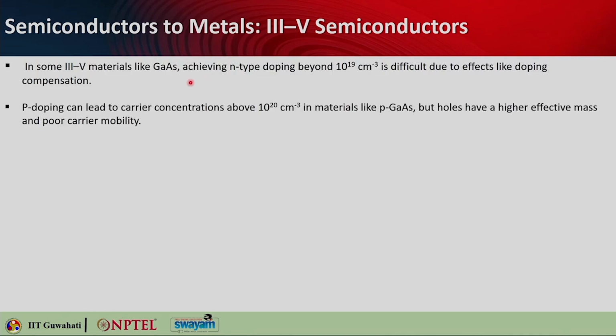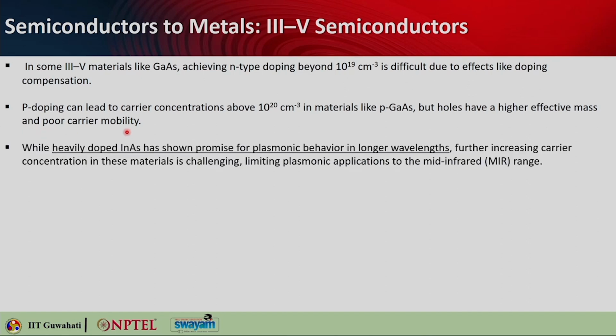In some III-V semiconductors like gallium arsenide, achieving n-type doping beyond 10^19 per centimeter cube is difficult due to effects like doping compensation, and p-type doping can actually lead to something above 10^20, okay, in materials like p-type gallium arsenide, but mu will be smaller in this case, right, because it has higher effective mass and poor carrier mobility. So, that will also not help.